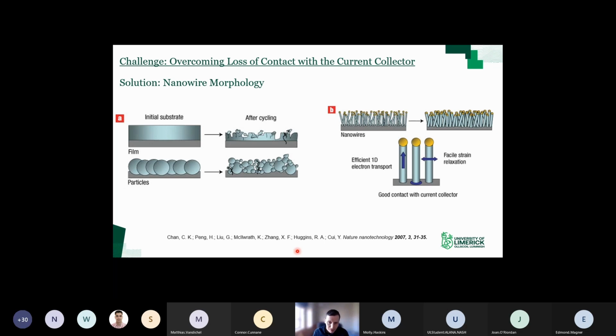What that does is, because every nanowire is directly contacted to the current collector, you get good electrical contact and efficient electron transport from the current collector. The nano dimensions then mitigate against pulverization. So nanowires won't pulverize. The stresses within the material, because it's nanostructured, are much less, so they don't crack and lose contact with the current collector. Now they do change their morphology, which I'll get to later, but they don't lose contact with the current collector, which is very, very important.